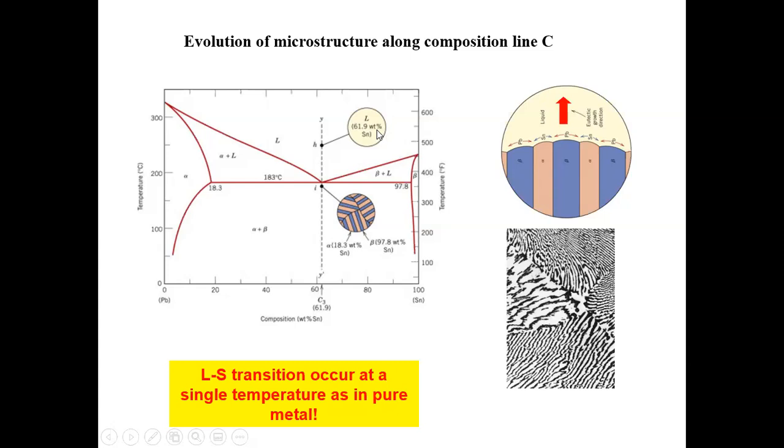So this is all I want to say about this, because we're going to reserve more details for later. So again, eutectic, I think the key point here is that eutectic is a very fast transformation. It's a well-defined thermodynamic phase transformation from a single liquid phase simultaneously to two different solid phases, alpha and beta, right? And at this transformation point, right at 183 degrees Celsius, you see that liquid coexists with alpha and beta, right? So during the growth of the eutectic, you see this part is liquid, and then you have this portion of solid growing, and in the solid you have both alpha and beta phase. So that is how you achieve coexistence of three phases. Does this make sense, everyone?